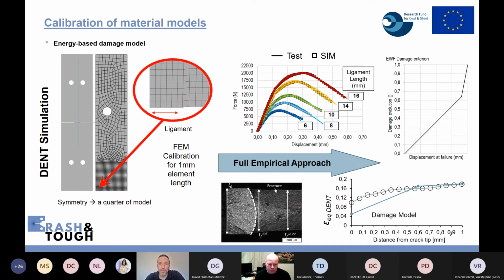Through the simulation of this test, we obtain the parameters of the failure model. You can see at the right the damage evolution curve, in this case defined in a bilinear way, and we are using an inverse engineering process, as Jorgen explained before, changing the model parameters to obtain a good fit between the simulation and the real test in terms of the force displacement results. And we do this for different ligament lengths. In our model, we work with shell elements, and the failure model was calibrated for 1 millimeter element length.